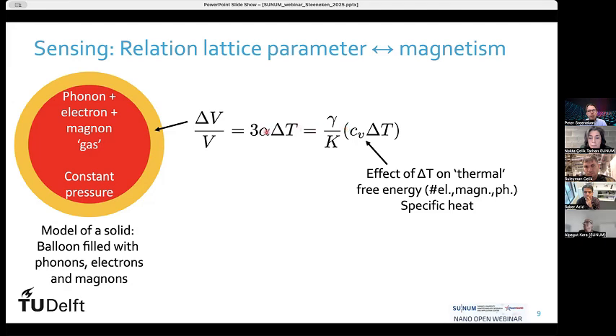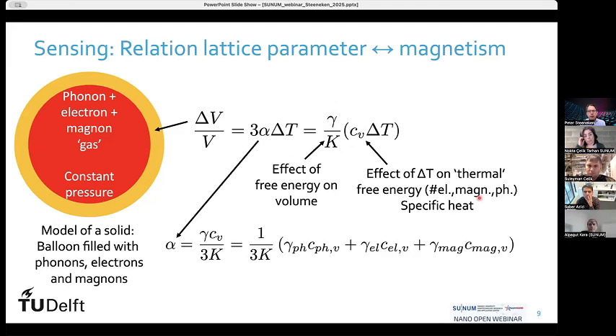And we can relate the two by this equation, if we also take into account this factor, which basically states what is the effect of this energy on the volume. So the volume change is a consequence of the generation of extra magnetic excitations in the material. Of course, you have magnetic excitations, but you also have lattice excitations, so phonons, which are lattice vibrations, and you have electronic excitations. By monitoring this thermal expansion coefficient, we can study the phonons, the electrons, and the magnons. So we can really study the properties of this material. And this prefactor consists of the Gruneisen parameter and the bulk modulus of the material.